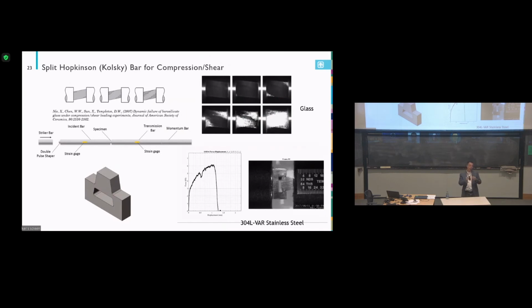So it's not uniaxial compression, not uniaxial tension. What about combined compression shear? It's going to affect the failure mode. So here, that's a specimen design. Another reference of work where we use an inclined specimen. This is the glass sample. It's not like this, it's inclined. Now we apply this load, you can see the specimen is subject to compression and shear.